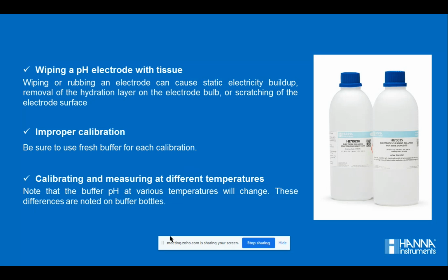Calibrating and measuring at different temperatures. If your buffers have different temperatures and your electrode or your meter is at a different temperature, then the temperature probe will calculate the pH according to the temperature. Thus, if your 4 buffer is at 15 degrees centigrade and your 7 pH buffer is at 20 degrees centigrade, then the difference of 5 degrees centigrade will create an error in the calibration, and thus it will either not take the calibration or will have some errors in the calibration, giving out inaccurate readings. Then you have to make sure either you use a pH meter with an ATC feature in it, or you use all the pH buffers at similar temperatures, in consideration with your meter.